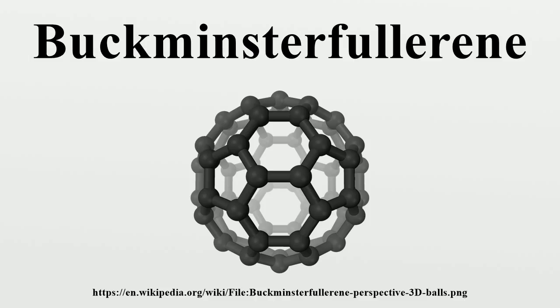Using laser evaporation of graphite, they found Cn clusters, of which the most common were C60 and C70. A solid rotating graphite disc was used as the surface from which carbon was vaporized using a laser beam, creating hot plasma that was then passed through a stream of high-density helium gas. The carbon species were subsequently cooled and ionized, resulting in the formation of clusters. Clusters ranged in molecular masses, but Kroto and Smalley found predominance in a C60 cluster that could be enhanced further by letting the plasma react longer.